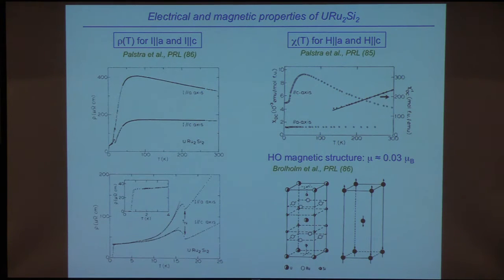And this early work generated some neutron diffraction experiments by Colin Broholm and co-workers. And basically what they found was that this was a C-axis antiferromagnet with this structure right here, but it had a magnetic moment of only a few hundredths of a Bohr magneton. Okay?